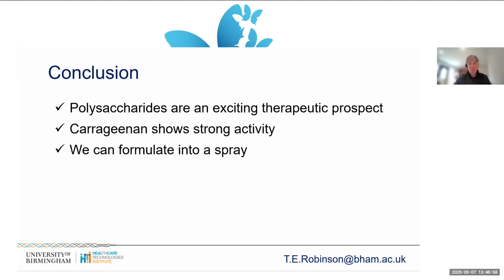It could. So as I mentioned, most of the research around polysaccharides has been for formulation things, material properties, particularly bulk material properties. So making things thicker, making things gel. What you can then do, and a lot of research people are, is combine that with smaller scale drug delivery systems. So as great as the material properties of these things are, if you've got for example a water-soluble drug, you can't really control the release of that. You put it in the polysaccharide matrix, and then once it's where it is, you can't really stop it from moving because it's in something that's 99% water.